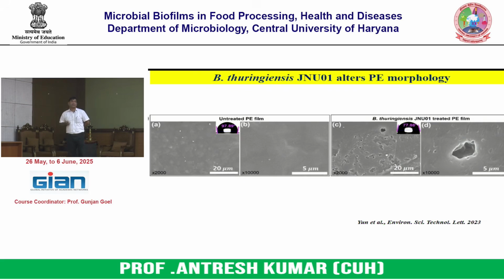They have also measured that once the microorganism adheres to the plastic, it increases the hydrophilicity. If the hydrophilicity increases, the water contact angle reduces. So this is the non-treated polyethylene film, and they measured the water contact angle, which is around 97 degrees. Once they treated the same material with Bacillus thuringiensis JNU1, the water contact angle was reduced from 97 to 77. It means the hydrophobicity of the polyethylene decreases. As a result, the water contact angle decreases with the action of this Bacillus thuringiensis JNU1.